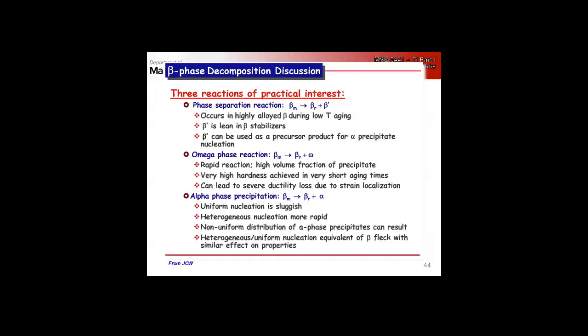The omega, very rapid reaction, high hardness because we get a very nice fine dispersion of precipitates, right? Ductility loss due to strain localization, right? Very much in line with the same things we saw with GP zones in aluminum, right? And then we have alpha precipitation, right? Uniform nucleation is hard to achieve. We have heterogeneous nucleation, right?